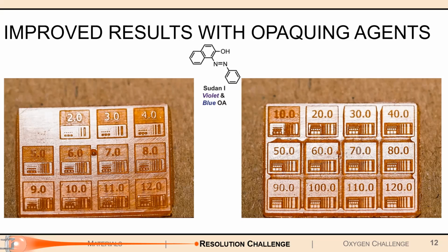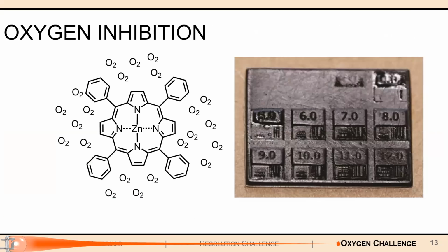Too much opaquing agent and you get nothing at all. But if you don't have enough opaquing agent, then basically their print looks really inaccurate, and then there's really no point to doing it. Additionally, there is another problem too that just simply comes from the oxygen we breathe in the air around us. What happens is that oxygen can come in, it can basically interfere and bind with these catalysts, as you can see right here.